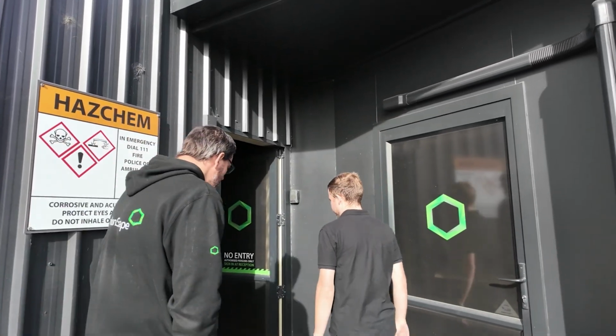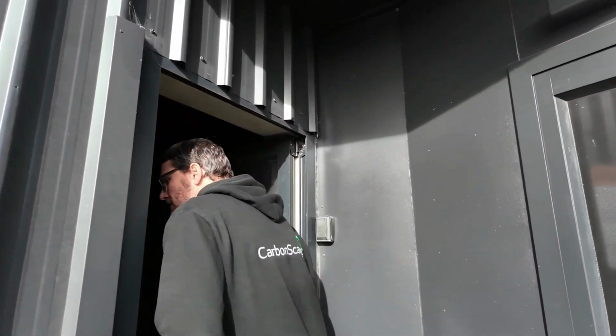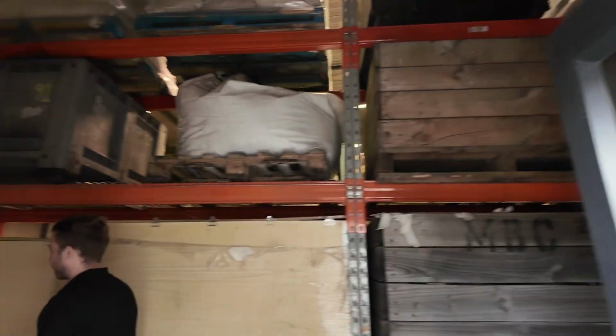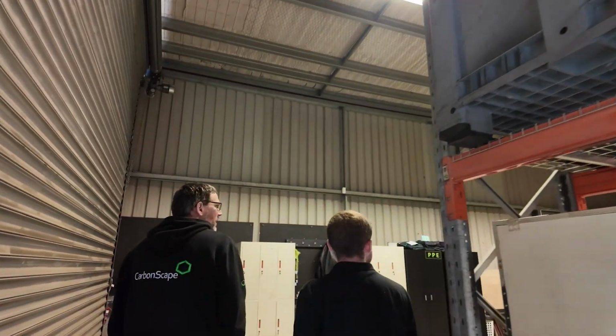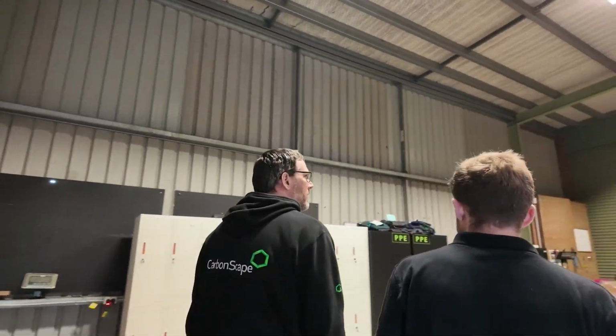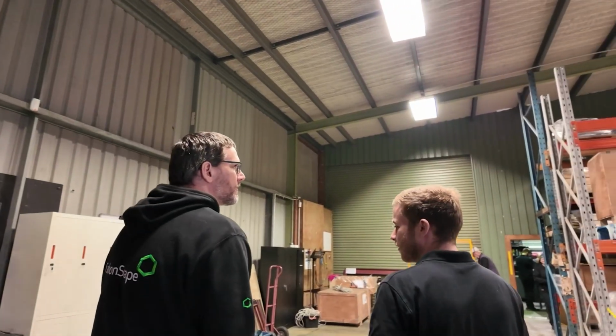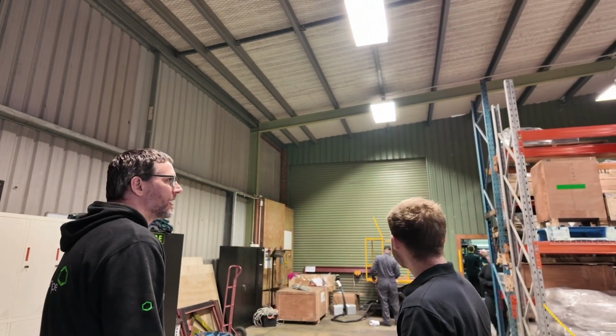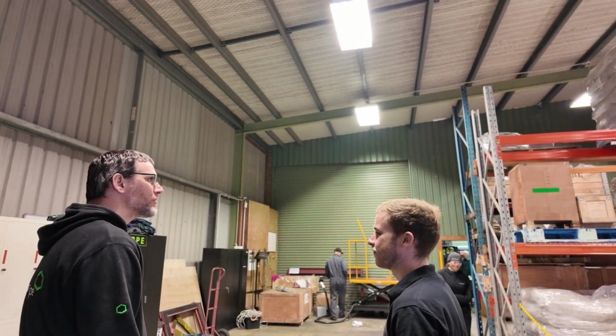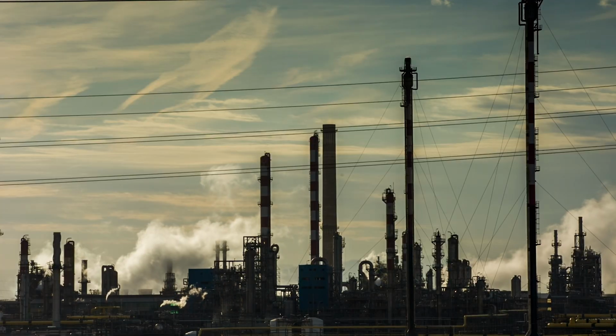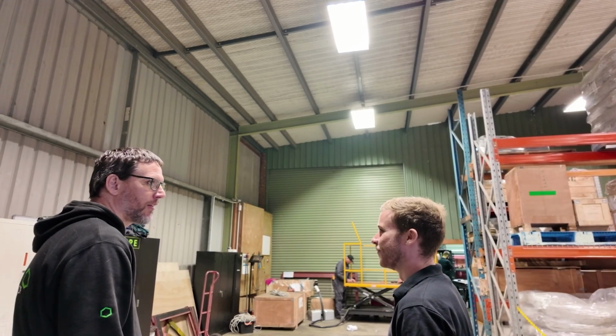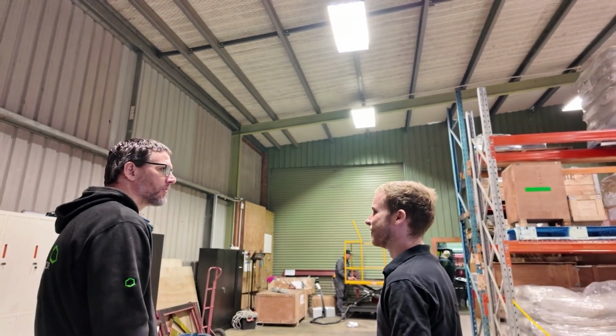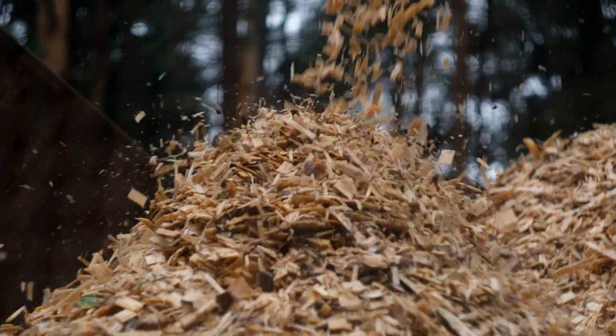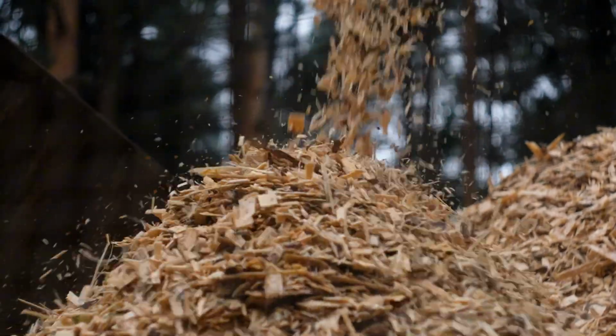Join me on a plant tour of their facility, where we walk through the full journey, from biochar arriving on site, through milling, graphitization, purification, spheronisation, coating, and finally, cell testing. CarbonScape's process is different from conventional synthetic graphite. Instead of starting with petroleum feedstocks and heating to around 3000 degrees, they use biomass and a catalyst, which allows them to graphitize at much lower temperatures.